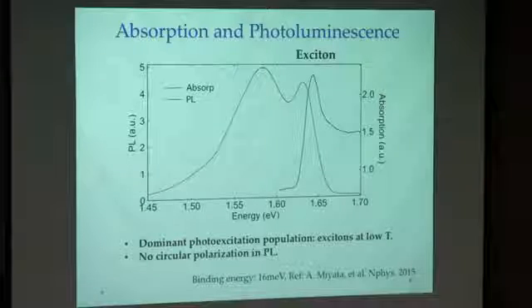This picture shows the absorption curve and the photoluminescence. And we can see the exciton absorption peak very well. Okay, we believe that it's excitons because of a recent experiment that determined the exciton binding energy to be 16 millielectron volt for the low temperature phase.